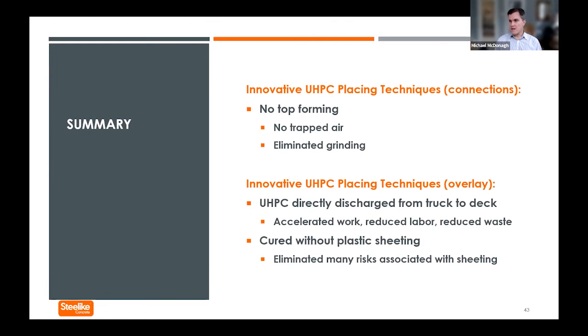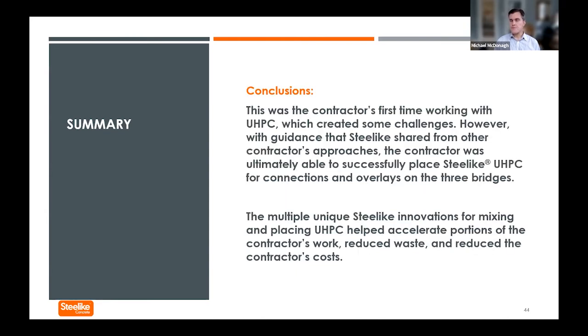And for the overlay project, mixing UHPC in a ready mix truck, again, brought advantage of large material production, but more importantly, the ability to discharge directly from the mixer, which was the truck, to the deck, accelerating the work and reducing labor and waste. And finally, curing without plastic sheeting, which eliminates the risks that plastic sheeting presents to a UHPC overlay.